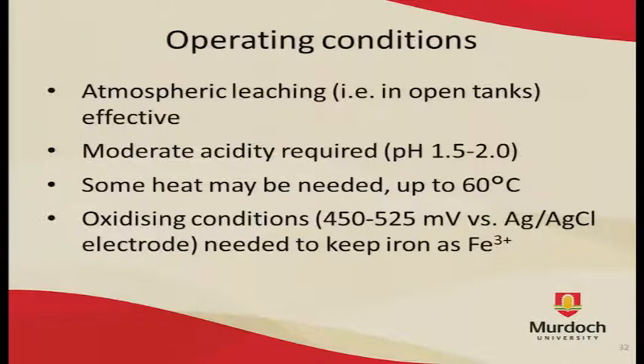Relatively mild conditions can be used most of the time. Atmospheric leaching is generally effective, with a bit of acid needed to keep the iron in solution. Lowering the pH will speed up the uranium dissolution, but it will also increase the rate of gangue dissolution, which in turn increases reagent consumption, so it's not always worth it. Heating may be necessary and, again, will increase the rate of uranium dissolution, but may also speed up the gangue dissolution more than it speeds up the uranium dissolution, and therefore might not be worth it.